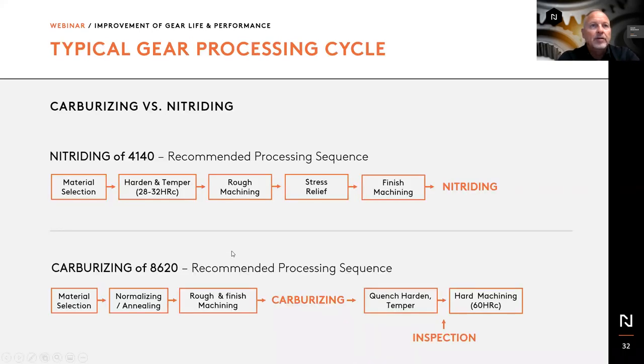So Jack had this slide up before, and I saw some questions come up on this. Typically in nitriding, what we do is we select the material, which Jack had mentioned already, it's a different material. We put some different alloying elements in there, which will add to the surface hardness, as the nitrogen combines with those elements. We harden and temper the steel first to get our core properties that we want for whatever process we have. We will rough machine, take most of the material off, which actually will impart some stresses into the steel. And then if you really want to control distortion, you do stress relief. This will take those stresses out, and then your finished machining will take care of your dimensions.